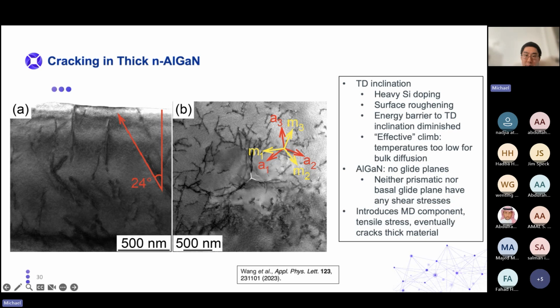Because of this, when you grow thicker, there is more and more tensile stress incorporated into the n-type aluminum gallium nitride. Now, aluminum gallium nitride is supposed to be in compressive strain on aluminum nitride because aluminum gallium nitride has a larger lattice constant than aluminum nitride, so the atoms are forced to squish down when you grow them on aluminum nitride. However, because of the introduction of these misfit dislocation components of these inclined threading dislocations, you introduce more and more tensile stress in the material such that you go from compressive stress to neutral to tension, and eventually the material actually cracks.